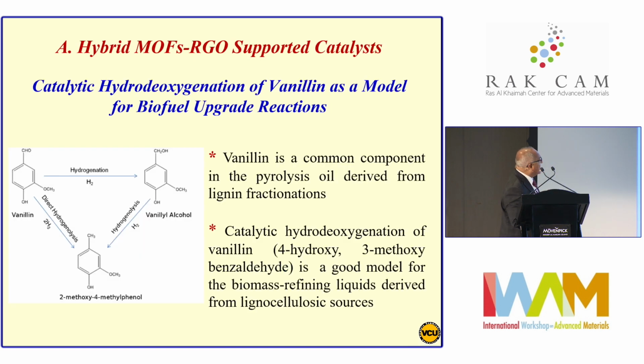So the first group of reactions, this is about upgrading materials for biofuels upgrading. And the reaction here is vanillin, which you can see here, which is a typical model system for lignin. And it's 2 steps: hydrogenation to form a vanillin alcohol, and then followed by hydrogenolysis to form methoxy-methyl phenol. This is actually the desired product. And you can think of this, if you have a good catalyst, as even 1 step going from vanillin directly to the methyl phenol. So this is important because this conversion allows you to make phenol, of course, which can be used as a biofuel in one way. And it also can go to a lot of manufacture of materials based on phenol manufacturers.